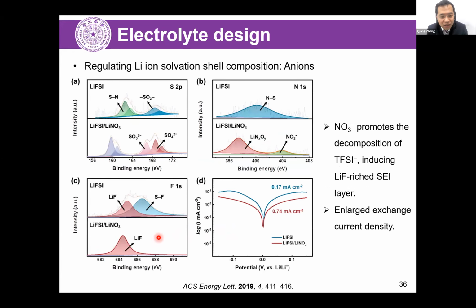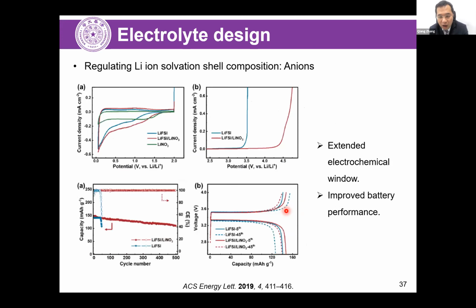And this renders the lithium metal anodes with an inorganic compound dominant surface, which gives the cell quite a large exchange current density, and this is quite important to help lithium ion diffusion in a working cell. The large exchange current density helps the battery with high rate performance.